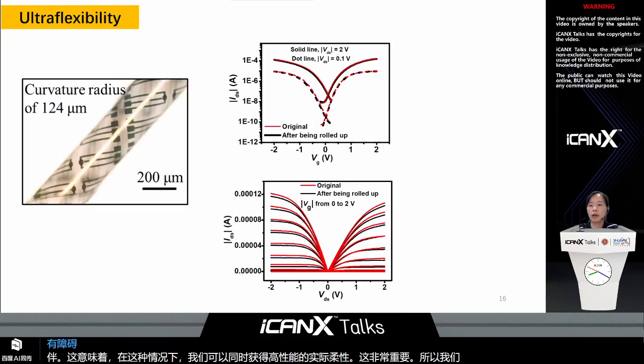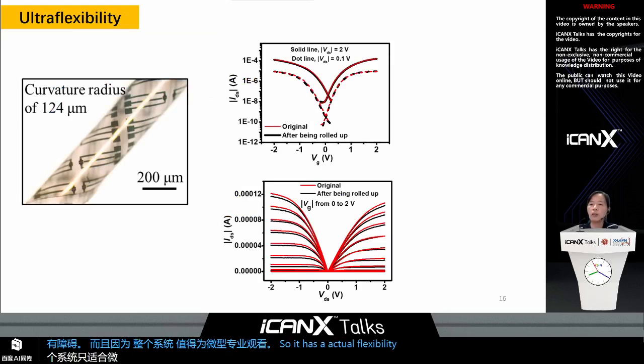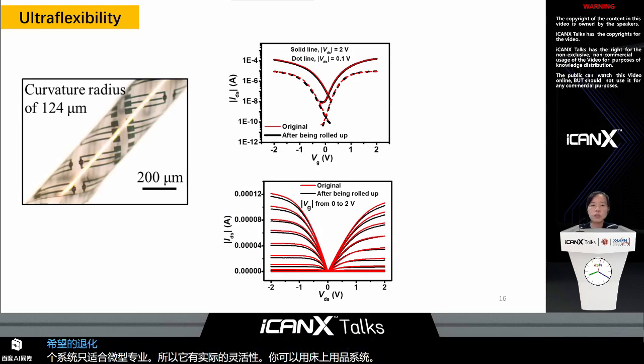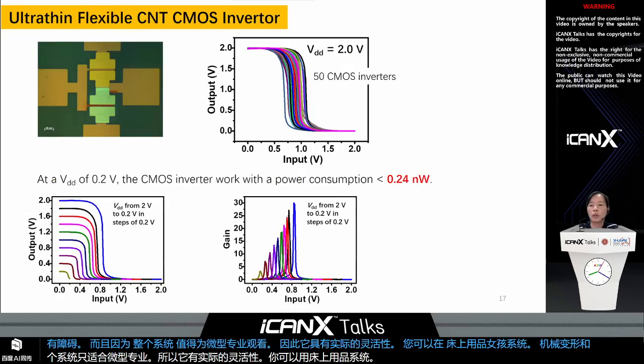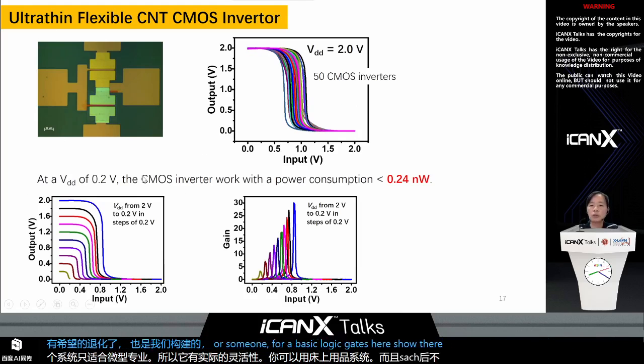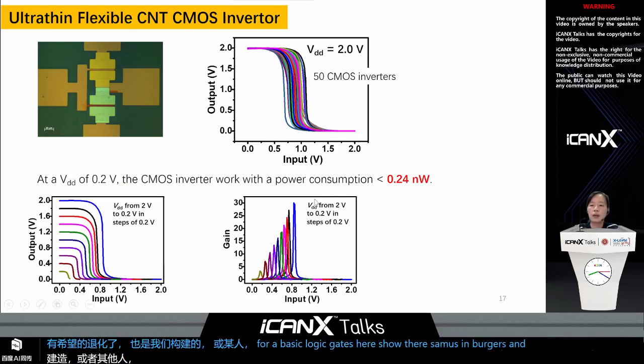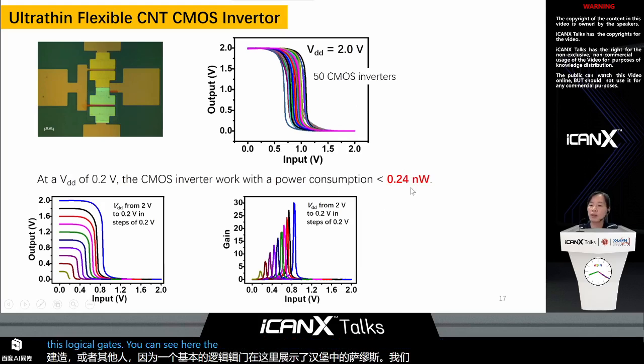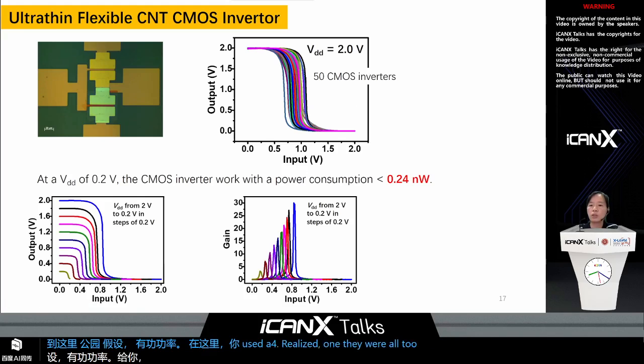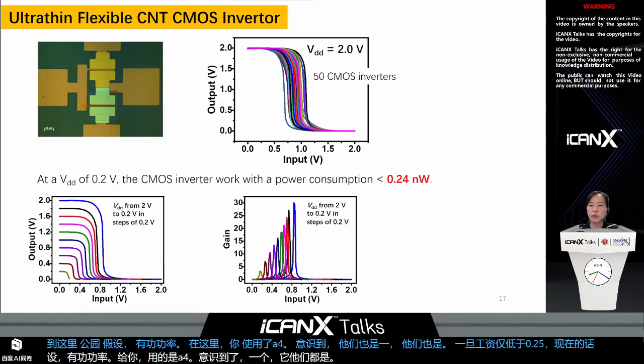And because the whole system is very thin, just 4 micrometers, it has ultraflexibility. You can bend your system, and there's no performance degradation after such mechanical deformation. We also constructed some basic logic gates. Here we show the CMOS inverters, and we checked the power consumption of these logic gates. You can see the active power used to realize one 0 to 1 switch is less than 0.24 nanowatts. It's a very low active power.